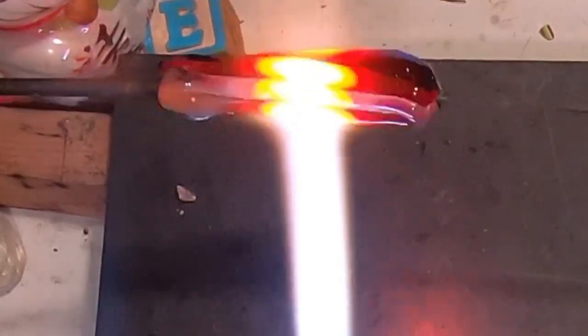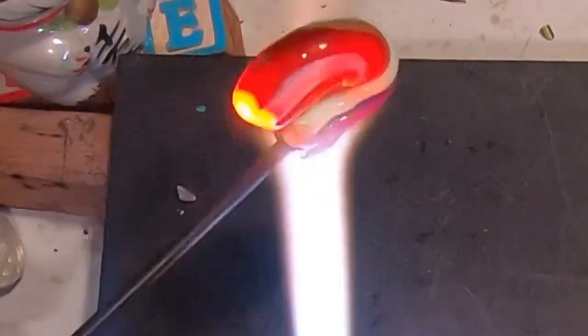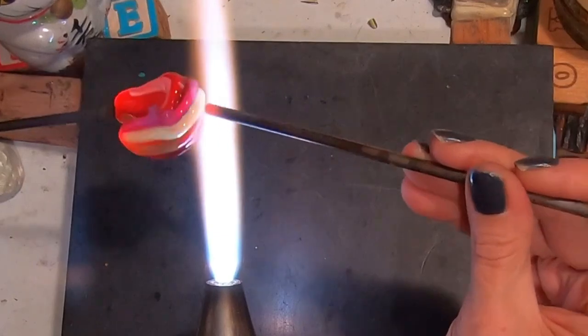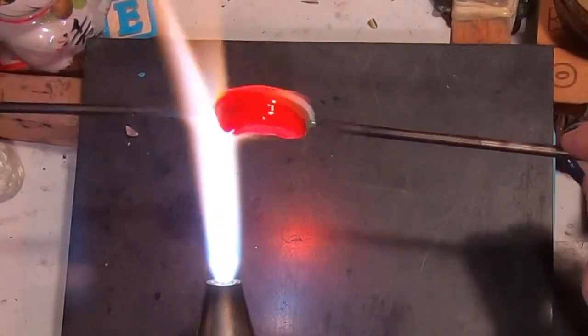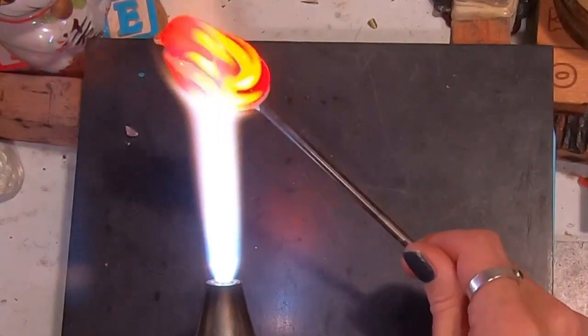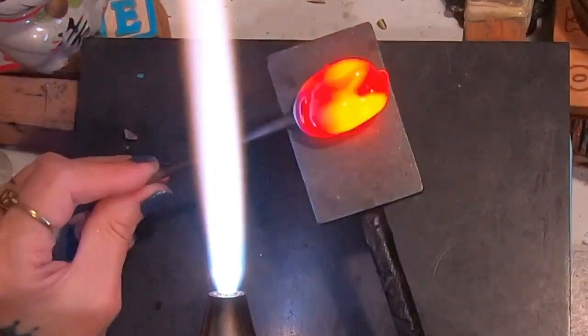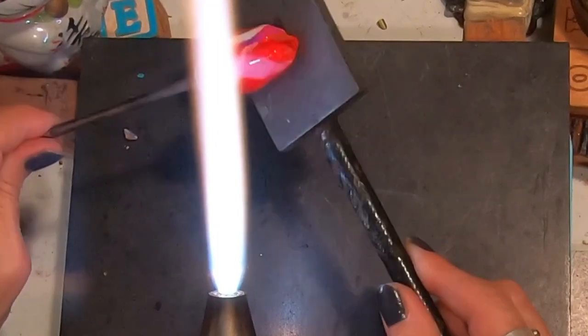When I heat the center I'm going to give it a really nice twist, then pull it back down toward the cane end — the punty end — and pull that little punty off. It's a lot easier to pull the punty out when it's really small. Then it's just a matter of getting everything evened out, putting on your other punty, and taking the first punty off to fix that area up and make it look more even. This does take time to melt everything together so you don't have any bubbles. If you notice any really hot spots there might be a bubble inside — you want to try to get that bubble to rise to the surface and pop, because bubbles in your cane may cause it to sputter and not lay down evenly.